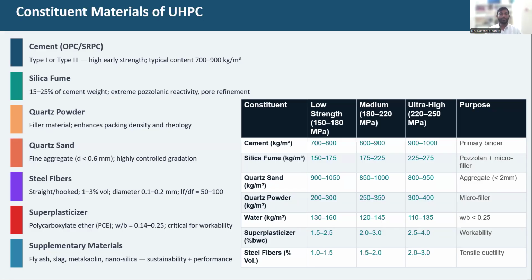So the materials include the cement, which is typically ordinary Portland cement. We cannot go with PPC, which is Portland pozzolana cement, and we know that PPC has a certain amount of fly ash combined with it. And when you have fly ash in your cement or in your concrete mix, that doesn't lead to early strength, but leads to later-day strength, that is at the end of 56 days. That's how we typically get it.